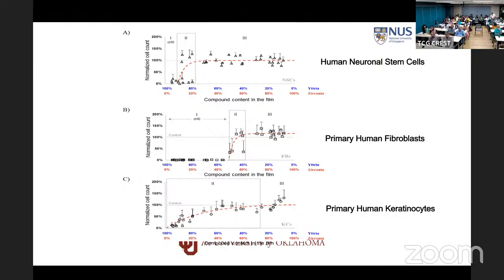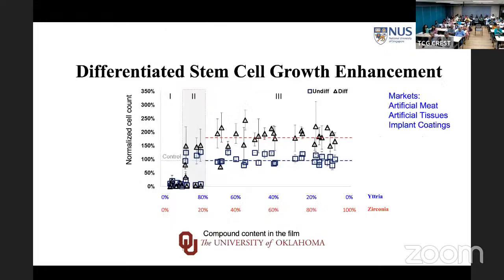So our strategy was to define islands of zirconium oxide surrounded by yttria. This is the project we're working on. One of the very exciting things is that we took differentiated stem cells, and this is growth on ordinary glass versus growth on zirconia. You can see there's a 200% enhancement in the cell growth. So it tells us that if I'm growing cells on surfaces, I can enhance the cell growth.